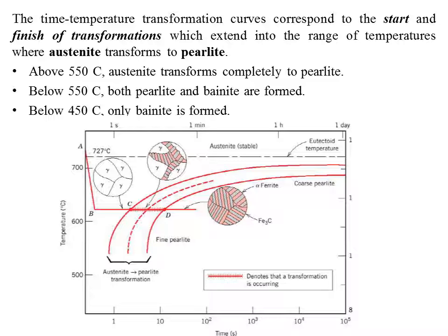The microstructure you can see here, how they are. At the midpoint, you will have a different structure. And as the time goes on, this is the timeline which is given, the red horizontal line, the microstructure changes. So from austenite you will have both pearlite and bainite at a temperature below 550, but below 450 you will have only bainite structure.